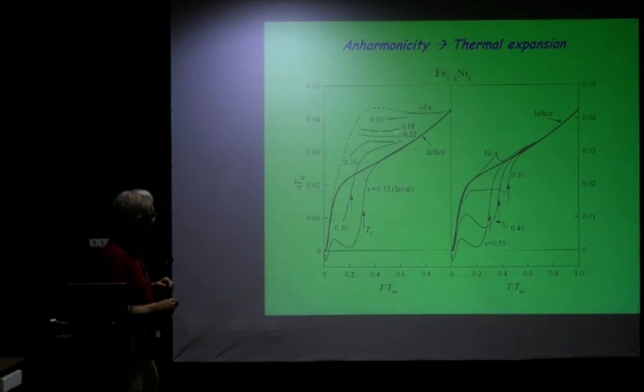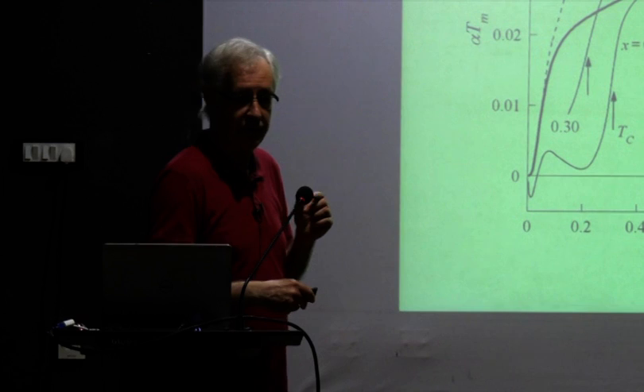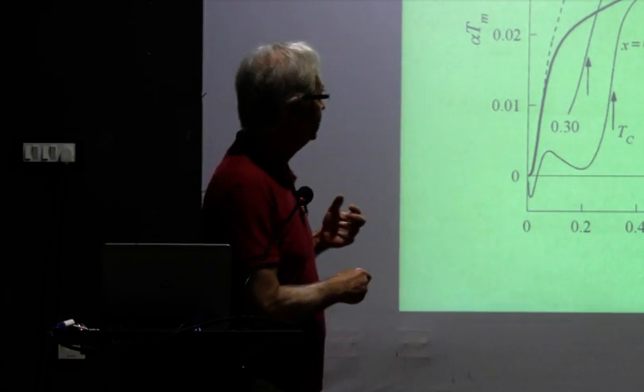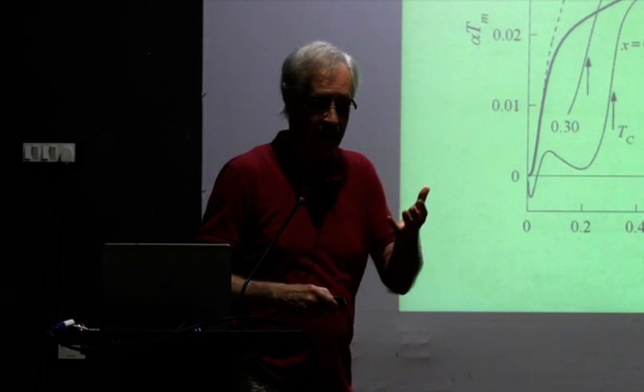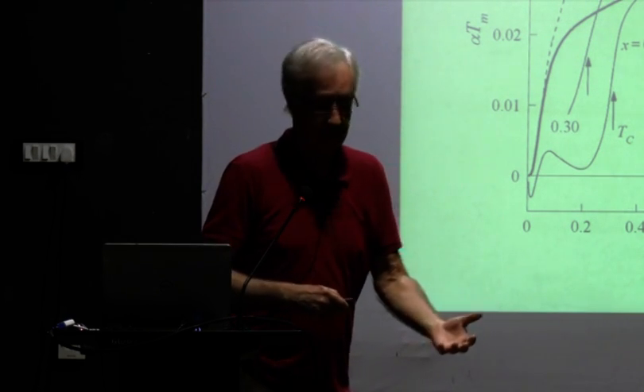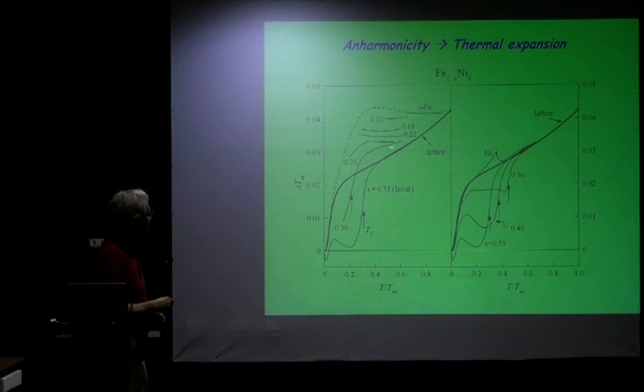And then we start increasing the amount of nickel. What is happening? We are gradually approaching the general lattice curve. But it's still anomalous. So iron itself is carrying its anomalous behavior along with it into the alloy. Then we come to this composition here, and this composition here starts doing funny things. In fact, this one also. When you measure this, you see that the thermal expansion coefficient lies firstly above this lattice curve, but then it crosses it.